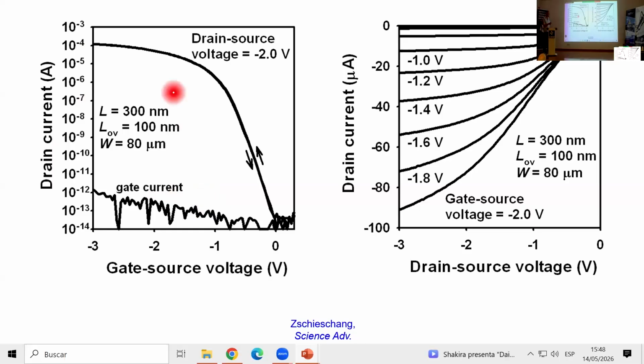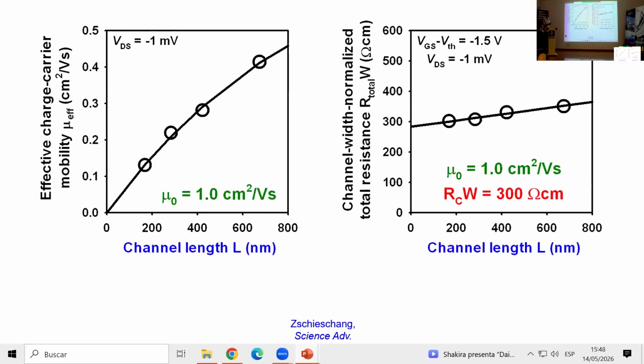Okay, and then those are the output characteristics, where the drain current is plotted as a function of drain source voltage. Okay, so we fabricate transistors with channel lengths ranging from, as you've seen, from about 200 nanometers to about 700 nanometers. And we characterize all of them. And then by plotting the parameters that we extract from the transfer characteristics as a function of channel length, we can extract values for the intrinsic charge carrier mobility and for the contact resistance.